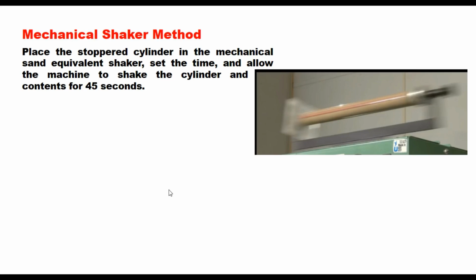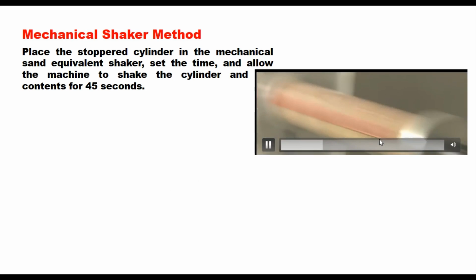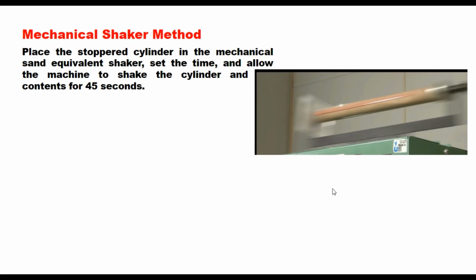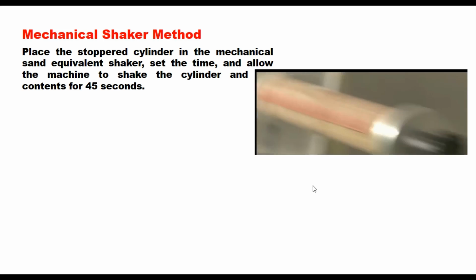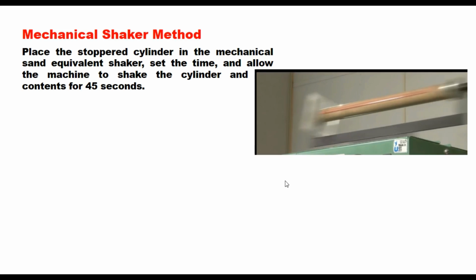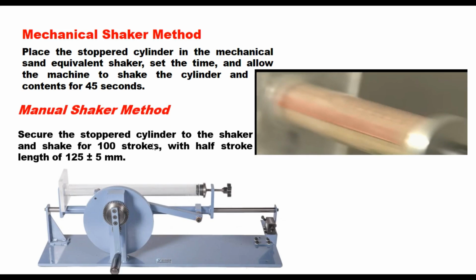When you are using the mechanical method, place the stoppered cylinder on the mechanical sand equivalent shaker. Set the time and allow the machine to shake the cylinder and contents for 45 seconds. When the manual shaker method is used, secure the stoppered cylinder to the shaker and shake it for 100 strokes with a half stroke length of 125 mm plus minus 5 mm.